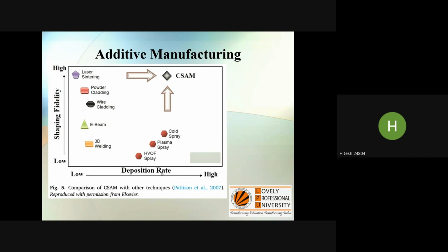So we are not integrating the plasma spray and HVOF process with additive manufacturing. We are integrating cold spray. Cold spray doesn't mean the temperature is in minus degrees. Cold spray means the minimum temperature which is used in thermal spray technology, so that is around 500 to 700 degrees Celsius. Like if you want to deposit aluminium, the melting point of aluminium is very low, but on the other side, ductility is very high. So those types of materials can be deposited by using this technique.